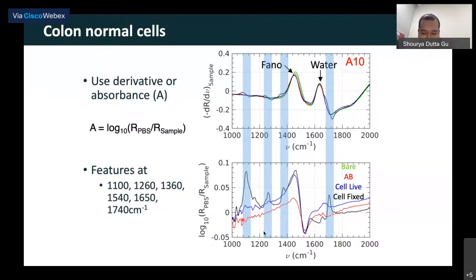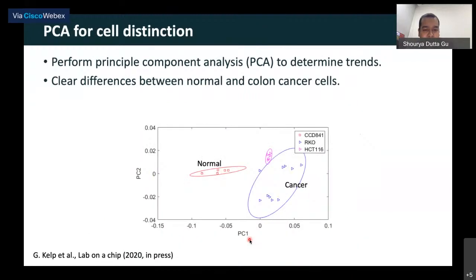But what you have to notice is that these features, in some cases, will go higher, and in some cases lower. So we cannot do it manually. So we do something called principal component analysis, right? This PCA allows us to analyze a very complex data set, and it tells us whether there is a significant difference between these two data sets or not. So here what we are plotting is the PCA scores, the principal component scores, between multiple sets of data. The horizontal axis is principal component 1 and the vertical axis is principal component 2.